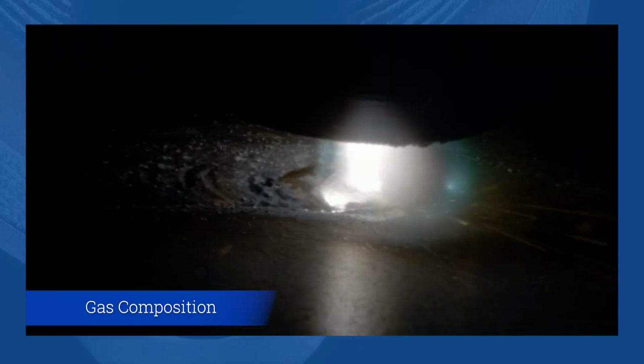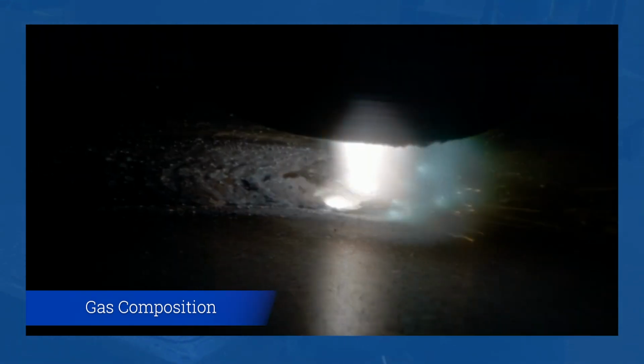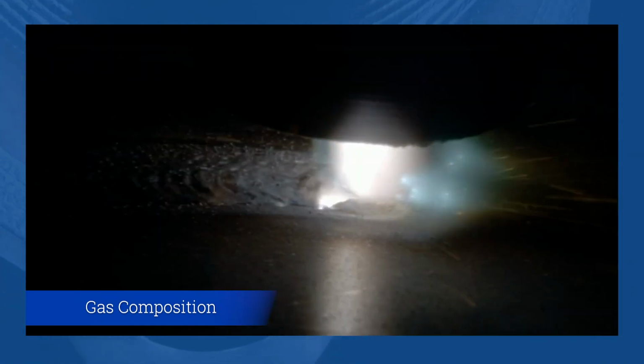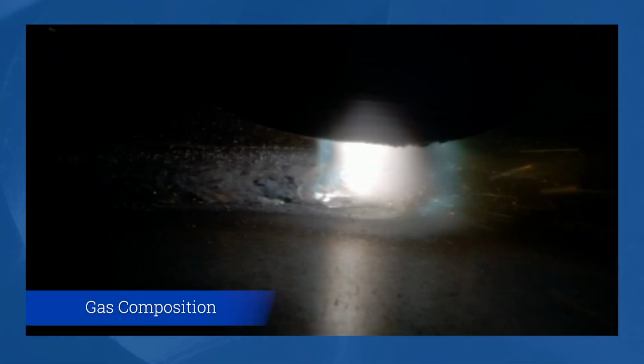The reason we're showing you this video is if you're running hydrogen, I want you to be able to identify when you have a hydrogen mixer problem. What you'll see is the edges won't wet, the welds will be more oxidized, and you simply don't get good fusion. Here's some good pulse parameters.